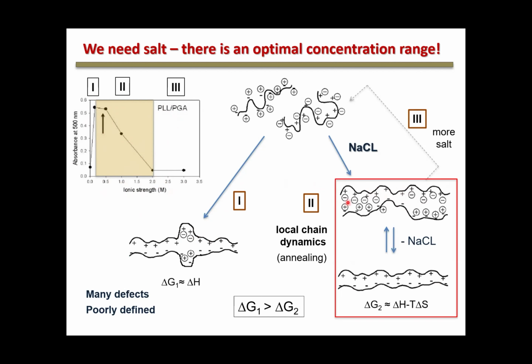then you will come into this equilibrium between extrinsically compensated charges and intrinsically compensated charges. And this will define the density in the polymer chain, the structure in the polymer chains, and this will result, hopefully, in so-called annealing. So polymers go from extrinsically to intrinsically compensated, forth and back, and finally can find the best combination with each other sterically, and this is what is called annealing, basically closure of the pores in the system when the system is becoming ideal. Ideally, they want to interact like that, one-to-one.